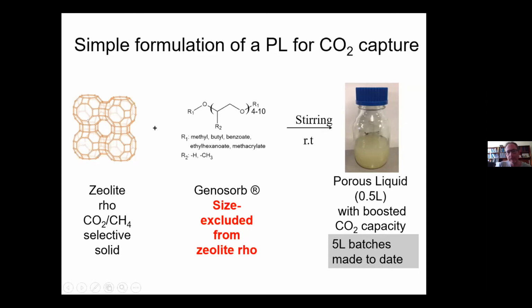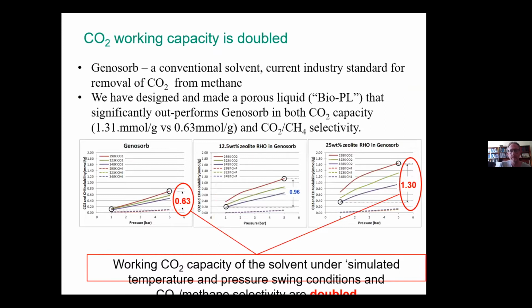So if we disperse this zeolite into this solvent, we've now got something that's a sort of milky looking suspension, and it has much higher CO2 capacity than the original liquid does. Showing you some data here. I'm not going to talk about this in too much detail, but essentially we looked at different pressures, different temperatures, imagining a sort of pressure and temperature swing process to deduce what the CO2 capacity was, the working capacity. How much CO2 can you pump in and how much can you get out?